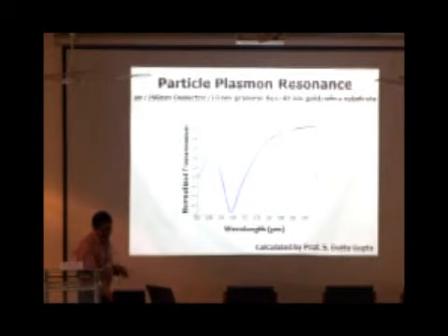This is a calculation, just to show that there is a plasmon, launch a white light and then look at the absorption corresponding to the localized plasmons. This matches with what we are seeing, showing that these are indeed particle plasmon resonances.